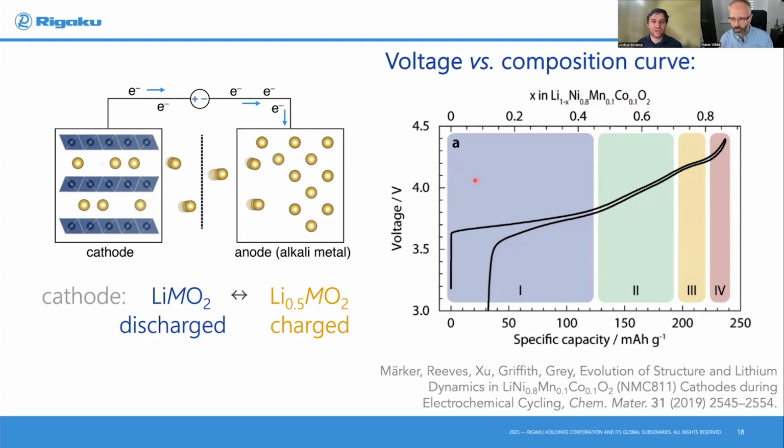And we're going to start fully lithiated. Then as we charge the battery, we pass current across the cell, and we are going to deintercalate lithium. And so our x is going to go up from 0. With this material, you can actually get 85 or even 90% of the lithium out. Your voltage will continuously go up as you do that, till you have an almost delithiated cathode. Then you can use this battery and discharge it, use it for some task, and then the voltage will go down, following ideally a very similar curve with low hysteresis. That's a sign of an efficient battery.